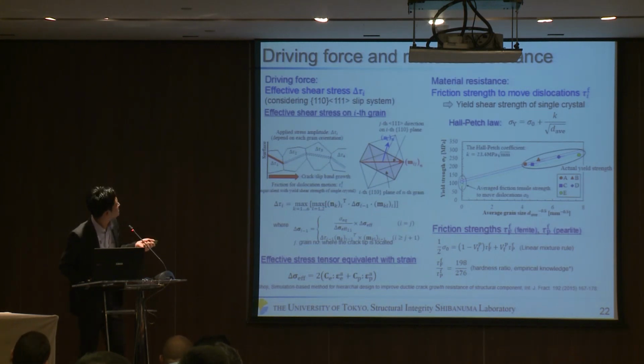And the material resistance is the friction strength to move dislocation. This is the yield shear strength of a single crystal, because yielding is caused by the movement of dislocation. This is employed as material resistance. And this is calculated by the Hall-Petch law.